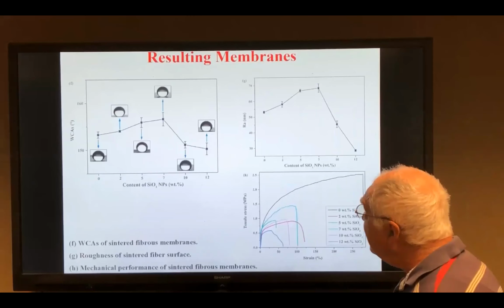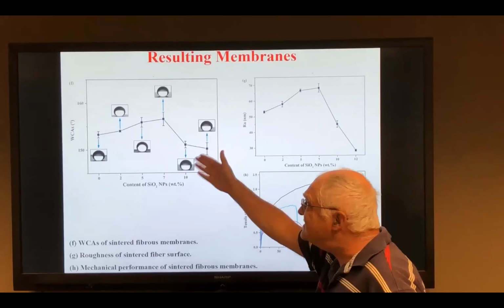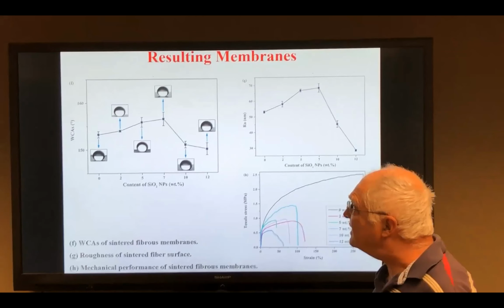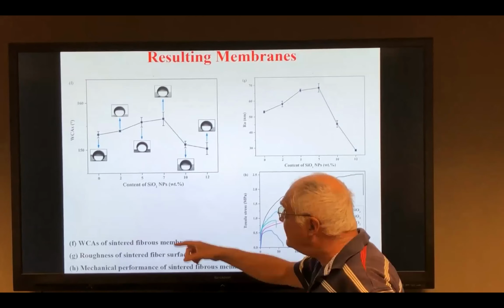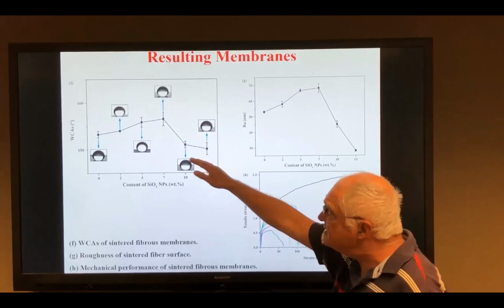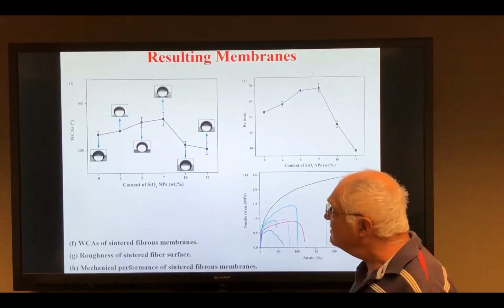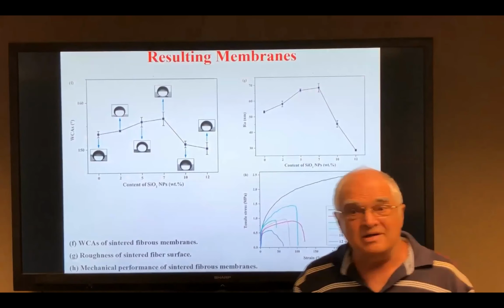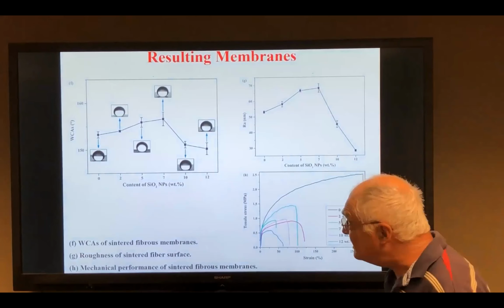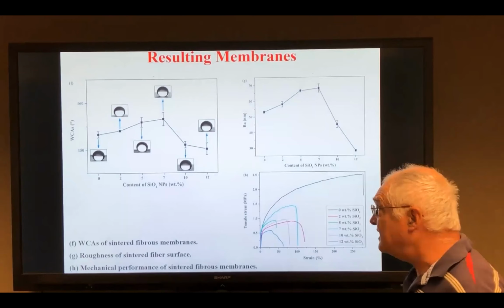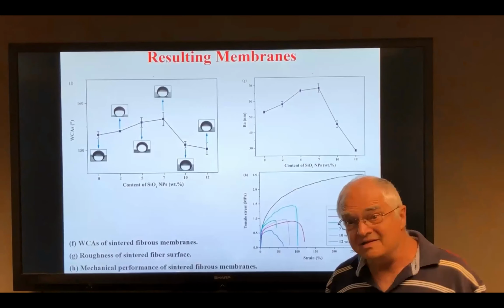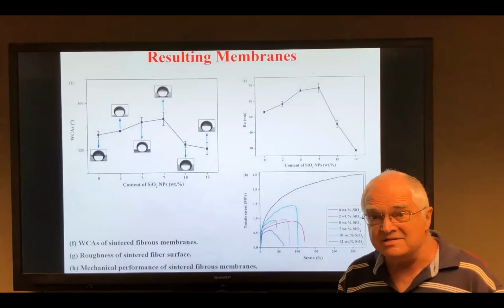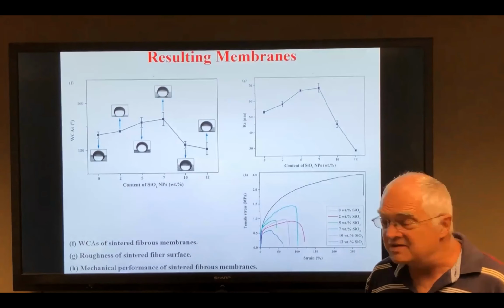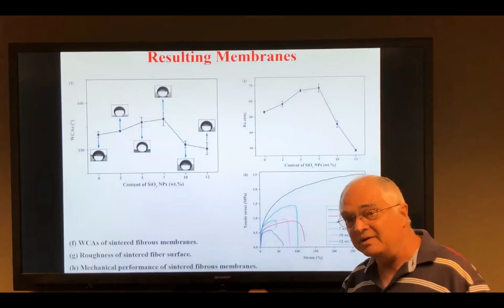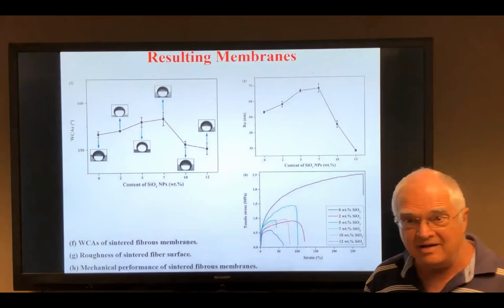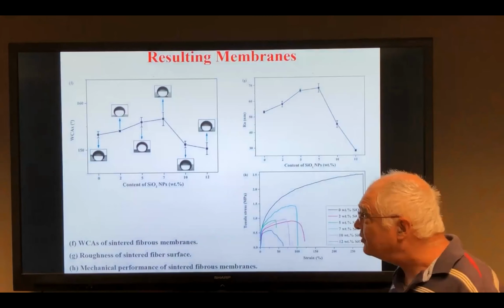Please go ahead. Then you also test water contact angle, so to what extent the membrane by itself is super hydrophobic. You put softly a droplet on top of this membrane, different compositions obviously, and you see that the contact angle is always about 150 to 160 degrees. So the material under this water droplet looks absolutely super hydrophobic, which is considered in this field a good sign, and in many cases it's considered to be the ultimate proof of super hydrophobicity. In the following, I'll show you that this is not the ultimate proof, and there are essentially no materials which can be super hydrophobic. Super hydrophobicity will be proven to be a conditional property.